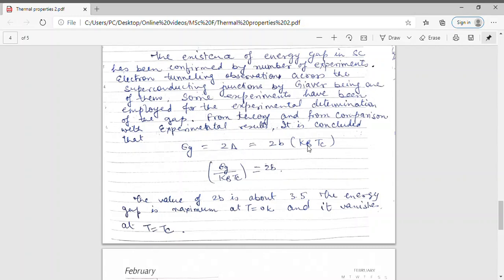Here kB is the Boltzmann constant, Tc is the critical temperature, B is a constant. From here the value of 2B will be equal to Eg upon kB Tc. This energy gap will be maximum at T equal to 0, and at temperature T equal to Tc, this energy gap will vanish. Why? Because here the material has become a normal material. And the value of this constant 2B has been found to be about 3.5. This delta is temperature dependent.